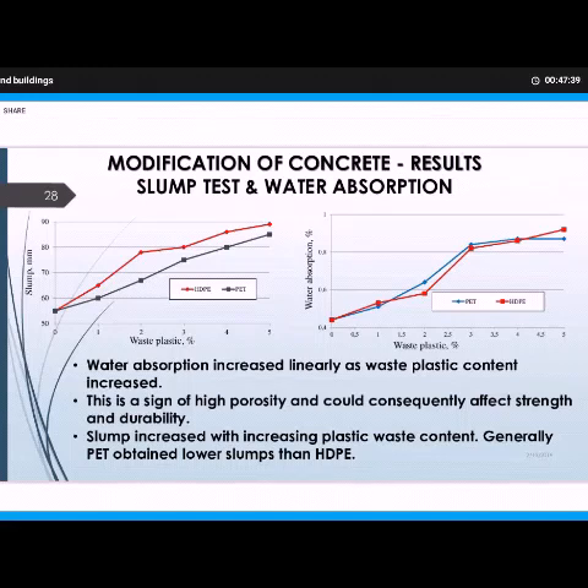And when you look at the graph on the right, it is talking about water absorption. Now, water absorption is a very critical parameter when it comes to concrete works or mortar works, because as much as possible, you want to prevent too much water seeping into the concrete. When you have water seeping into concrete or other chemicals seeping into the concrete, it can lead to chemical reactions inside the concrete, thereby leading to lower strength and eventually poor durability. And so as much as possible, you make sure that the concrete is without pores. And so it is very crucial for you to check if you add the plastic waste, pores are created as a result of the plastic waste.